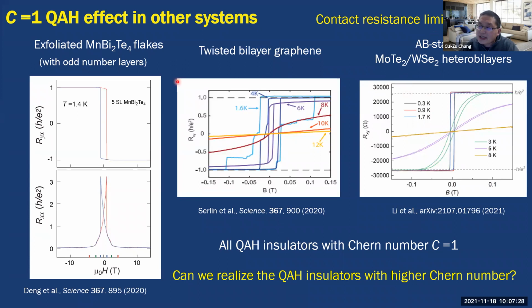We see that in all these systems, including the chromium- and vanadium-doped TI system, the Chern number is always 1, and the Hall resistance is h over e squared, which is 25.8 kilo-ohm. In this kind of quantum anomalous Hall insulator, the Chern number is 1. We notice that in quantum anomalous Hall, as I just introduced, there is this pinching chiral edge state, but the contact resistance is still huge. It's h over C e squared.